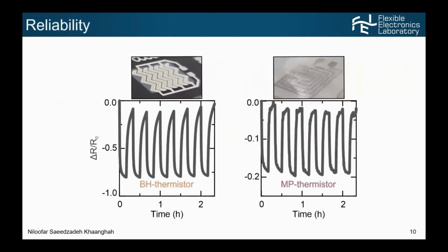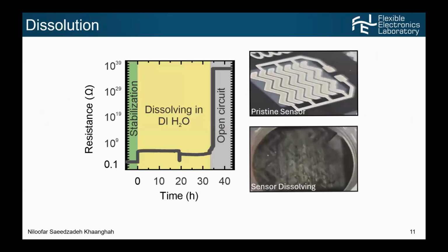Here you see the reliability test of the sensors, showing that our sensors have quite reliable signals over multiple cycles. And finally, we also did the dissolution test. We already have papers showing that IGZO semiconductor is dissolvable. However, what they did was they used a dissolvable substrate and had IGZO on top. And when they did the dissolution test, it was not clear whether it was the substrate or the semiconductor dissolving. But here we aimed to show whether IGZO is dissolvable or not.